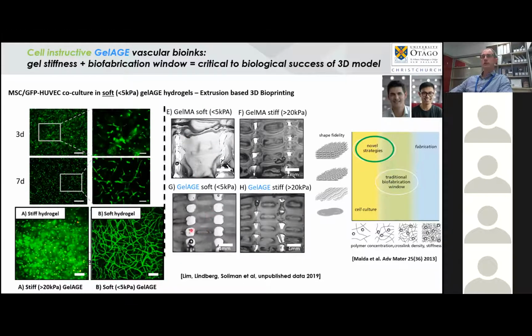But what we can show is that the advantage of gel is that you can have printable constructs with good shape fidelity that are soft as well as stiff. And so you can start to tailor those microenvironments for what you would really like to achieve. That's really starting to address some of the novel materials needs in biofabrication these days: we would like tunable constructs which give you shape fidelity, so you can get cells placed wherever you like in a hierarchical structure, but with a relatively soft, permissive environment that's cell instructive.